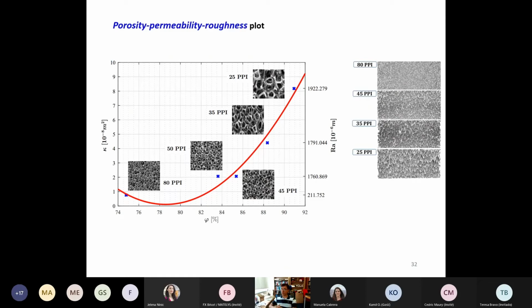If you measure all those parameters, you can come up with this rather complex figure. You can see on the x-axis is the porosity. For the cases we consider here, they are often over 70%. On the left y-axis, you have the permeability, and on the right one is the roughness factor. So we call it a porosity permeability roughness plot. 80 ppi, 50, 45, 35, and 25 ppi have been tested for these particular measurements.